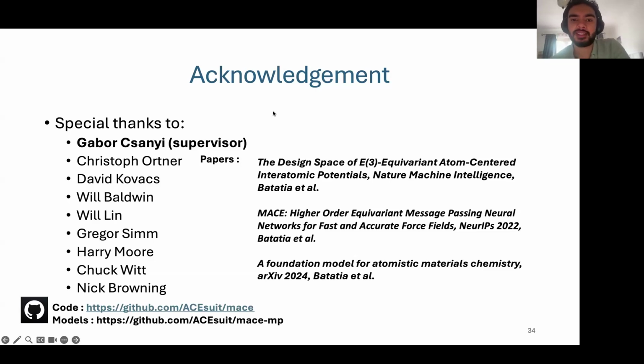The way you do that is you take a standard part of the Materials Project, you reevaluate your foundation model on it, and then you use as the replay set the energies and forces labeled by your foundation model. So you are really replaying your own predictions. And this has proven to be quite useful. In the next version of MACE, this will be the standard way to do the replay fine-tuning. I wrote some documentation, and if you want early access, you can use the develop branch for that.